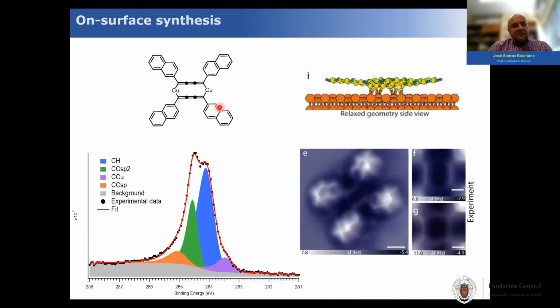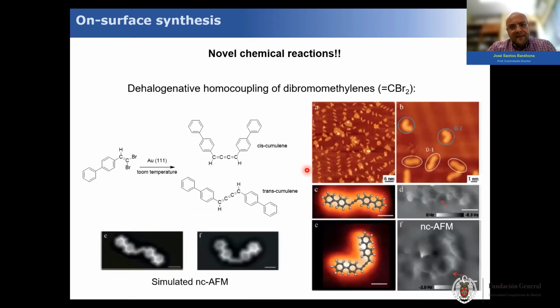We can also run XPS on the samples, and we confirm the presence of the organocopper linking between copper and carbon by this small shoulder here of the convoluted XPS curve. Another example of novel chemistry is this one presented by a Chinese group in 2017, where a dibromovinylene functional group deposited on top of a gold surface undergoes the transformation into a cumulene.